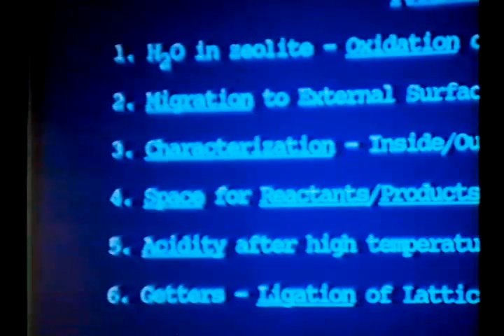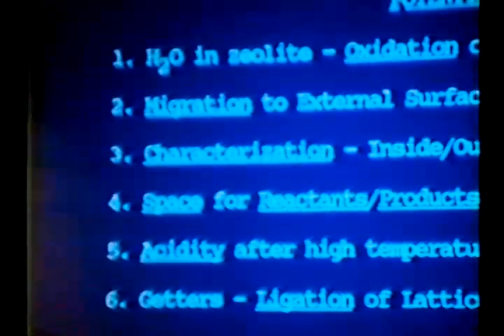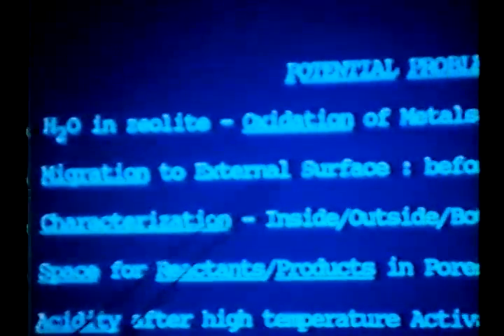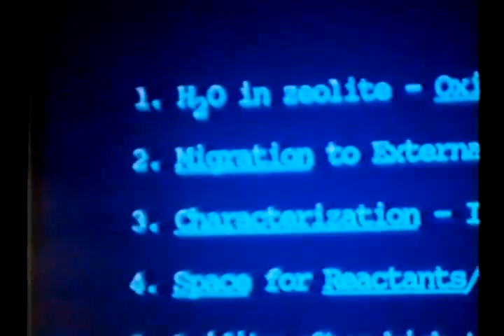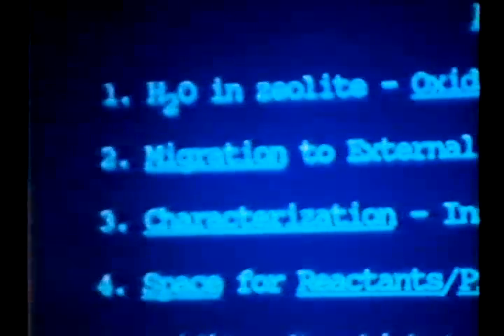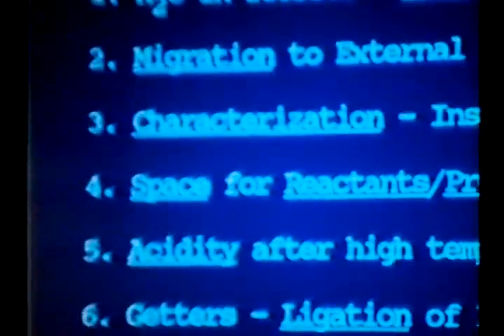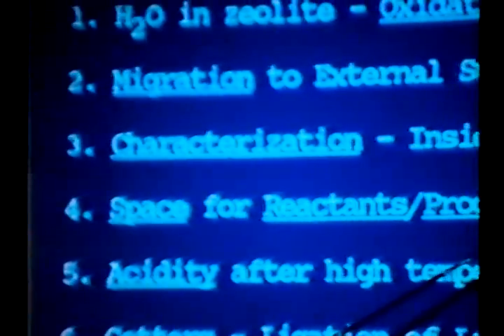Well, what are some of the problems of encapsulating a metal complex in the zeolite? What are some of the potential problems? First of all, there's a lot of water in the zeolite, and that could oxidize the metal. You have to worry about that. The second thing is that if you've got a metal inside a pore and you're going to heat this material during a catalytic reaction, it could come outside. And you'd like to try to prevent that, too. It can move either before you use it or while you use it.